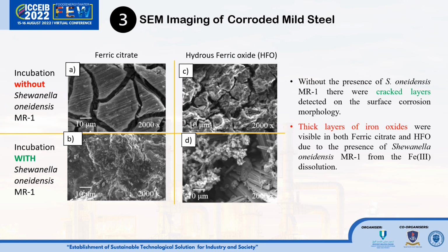To sum up, we suggest that Shewanella indeed transformed these iron oxide corrosion products into metastable minerals, causing Shewanella in the early mass loss testing to inhibit corrosion due to the iron oxide formed, which acts as a physical barrier against corrosion. While for incubation without Shewanella, we can assume that the accumulation of ferric iron in the vials created a very corrosive environment, especially in the presence of citrate ions, because at a higher concentration of the corrosive ion citrate, it can rapidly corrode the steel surface at higher rates of corrosion.